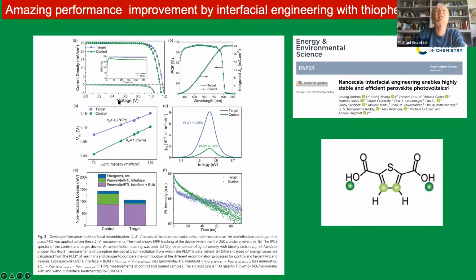You can see that here in the photovoltaic performance. We have the typical photocurrent voltage curves, the so-called JV curve, and this is the IPCE, the incident photon to current conversion efficiency. We get over 90% of incident photons converted to electric current, and these cells reach 25 milliamps, which is a high photocurrent, and close to 1.15 volts. So high voltage, high current, good fill factor.